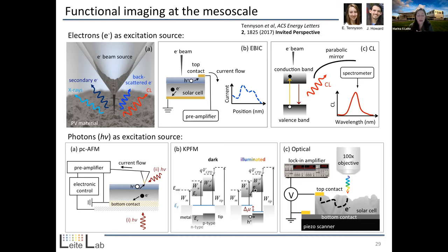And another thing that I want to say is that we actually don't need to have atomic scale resolution here. So for those that do scanning tunneling microscopy, and I've done that back in my PhD in the synchrotron lab for a while, it's a super cool, neat technique, no doubt. But here we actually do not need atomic scale resolution. We're dealing with processes that are happening at the mesoscale. We're interested in the contribution of thousands of atoms, so we're talking about length scales between 5 nanometers and 100, essentially.